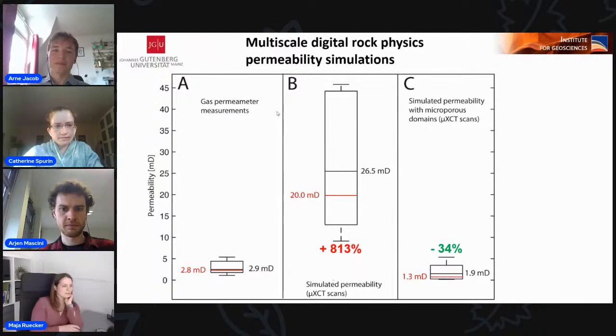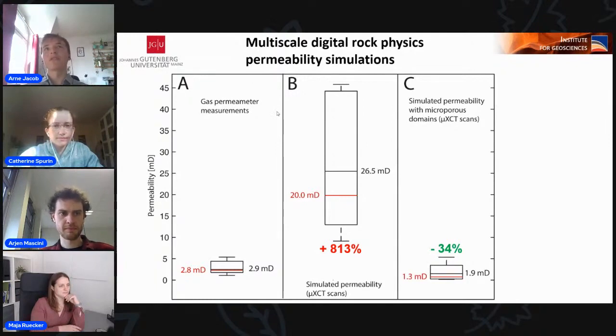Can you tell us already what parameters you checked? So what did you evaluate? Is it just the image processing? What kind of comparisons did you do? So what we already know is that the image processing is very important because even minor changes in the pore throat distribution might have a large impact on the permeability of samples. Yes. We assumed after Saxena that our scans were very good, that we had a good resolution, and that we were able to resolve the pore throats very well. So as soon as there are no better synchrotron measurements below 1 micrometer, I'm not sure how we should resolve this. Yeah. Okay, thank you. Looking forward to the paper.